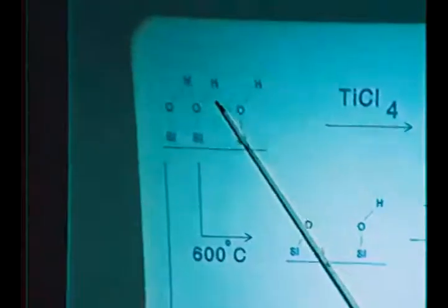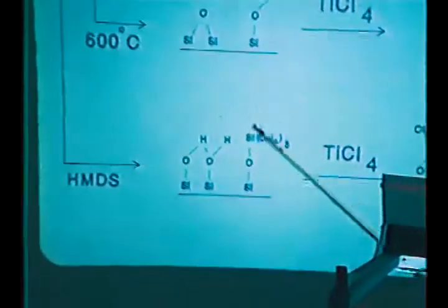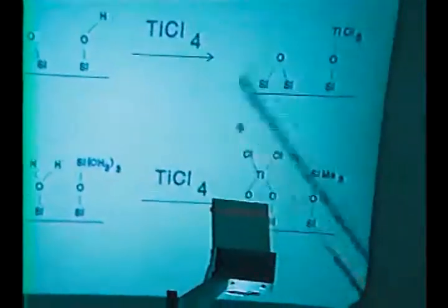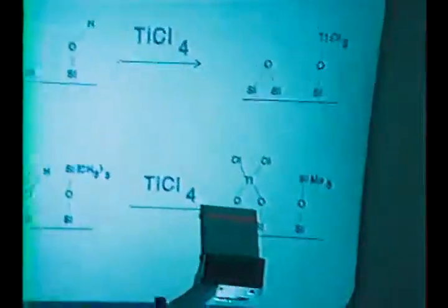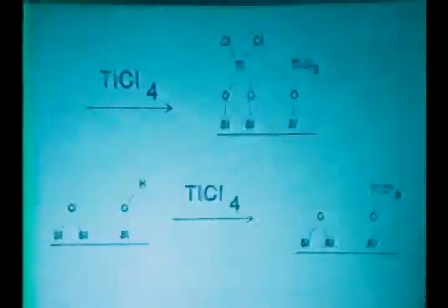On the other hand, if you take your silica gel and then react with the organosilane, it selectively silylates the non-hydrogen bonded silanols. Take that and react it with titanium tetrachloride, you get predominantly the bridge bonded species. So what we've been able to do at this point then is to essentially make different types of catalysts and characterize them with either one or two bonds to the surface. And the question then is, okay, that's great, let's do some catalysis finally and see what the differences are.